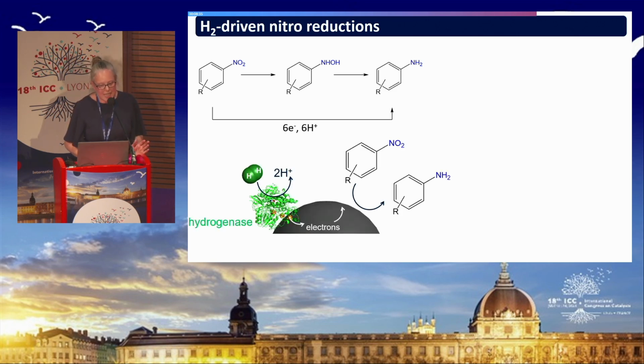Nitro reductions can happen on a carbon surface, and a lot of the work we do is with enzymes immobilized onto a carbon support. And so we hypothesized that the reduction potential for the nitro group on aromatic compounds is compatible with the hydrogen potential, and that we should be able to set up a catalyst that involves hydrogenase on carbon, where the carbon support is able to reduce the nitro group.